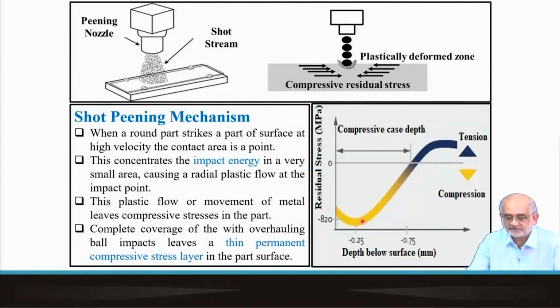What is very important here is to look at this curve. What we are seeing is the stress magnitude, and this is the neutral level. On top we have the tensile component. So the material in blue is in tension and the material in yellow is in compression. From the surface, the peak of the residual compressive stress is not necessarily at the very surface itself, because you can easily make out that this kind of deformation zone, or the so-called dent, creates the maximum accumulation of strain or dislocation density, not at the surface, but below the surface. So the peak residual compressive stress is at a subsurface region. In this case, it's at the 0.25 millimeter region, and then it gradually moves towards zero and then becomes positive.